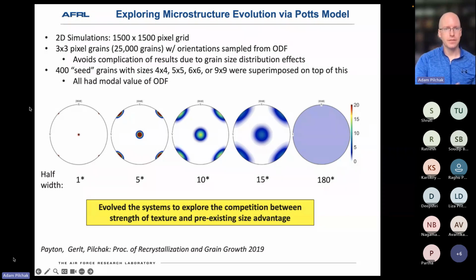And so this is a representation of the textures for a variety of initial conditions. We created just 2D simulations in this case, although SPPARKS can easily handle 3D. But in this case, we created an array of 3x3 pixel grains, so 25,000 grains in all, that had orientations sampled from the ODFs that are shown below. So we had very sharp textures with this initial rotated cube, and then we would introduce various half widths of that texture component, going to 5, 10, 15, and then ultimately 180 degrees, which is just a completely random texture. And we chose these simple, constant grain geometries just to avoid any complications in interpretation due to grain size distribution effects.